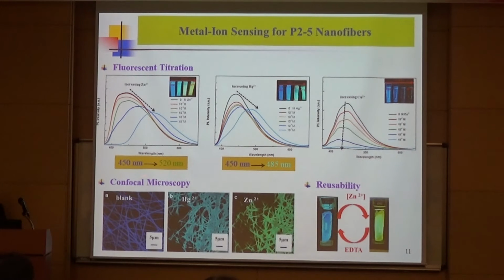And from the confocal images of this blending nanofiber after immersion in aqueous solution with an accessible amount of mercury ion or zinc ion, we could observe a visually distinguishable color change from blue to blue-green or from blue to green, respectively. In addition, this blending nanofiber could be regenerated by treatment with chelating agents such as EDTA to remove the binding metal ions.